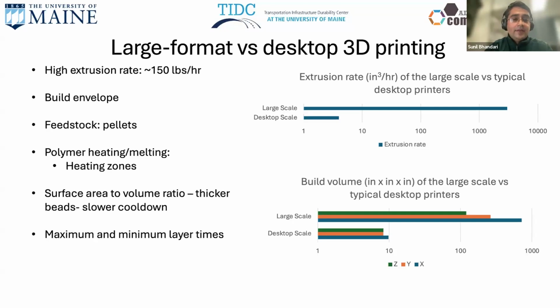And even though the printer can print 150 pounds per hour, for the parts we manufactured in this research, we could only print about 40-50 pounds per hour because of the limits on layer times.